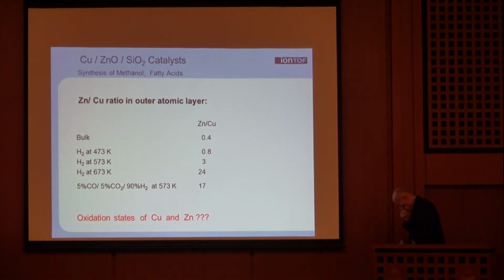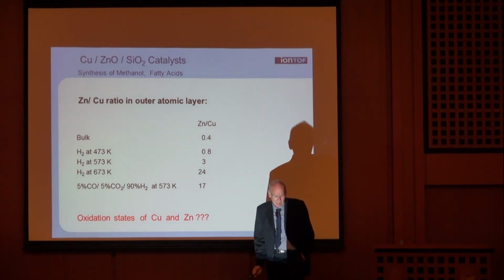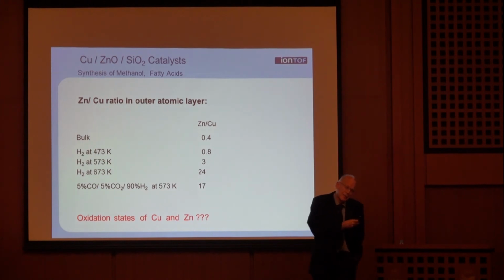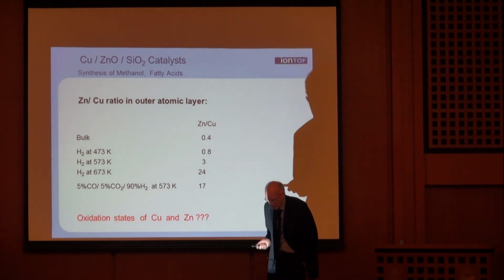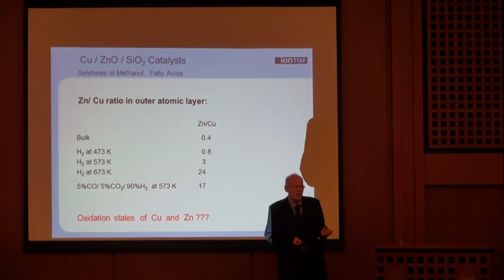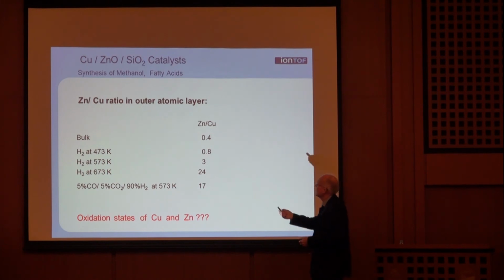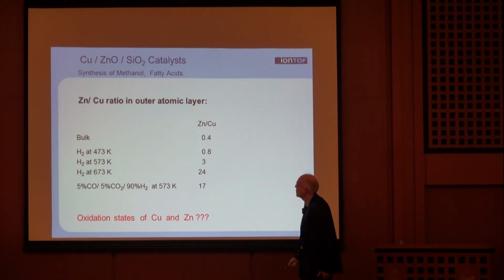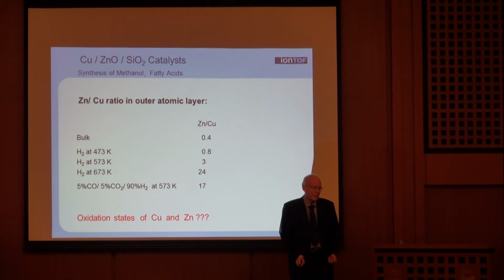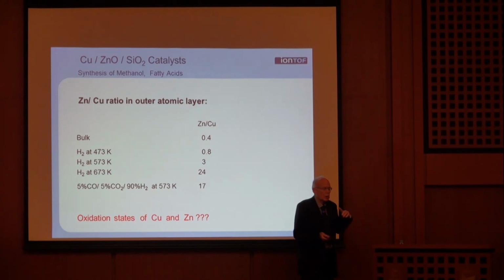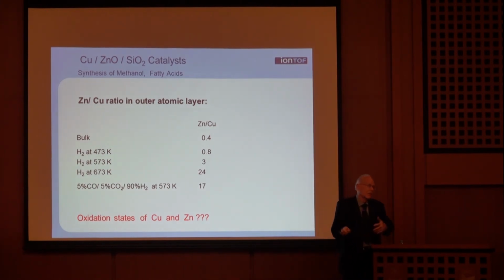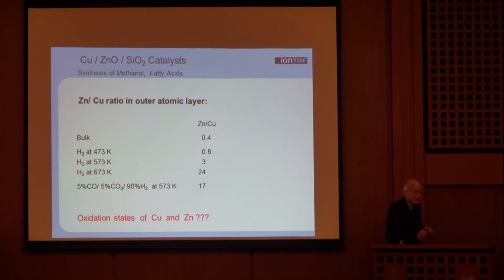Another example. Since probably many of you are chemists, and I'm a chemist originally by training, you say, well, okay, it's nice, good to know that there is platinum or gold, or in this case, things like copper or zinc in a special methanol synthesis catalyst. That's great, fine, and it's important. However, what we are really interested in is the oxidation state. And normally you would say, okay, then we go to other techniques, like, for instance, a very powerful technique, XPS. However, there's also a problem.